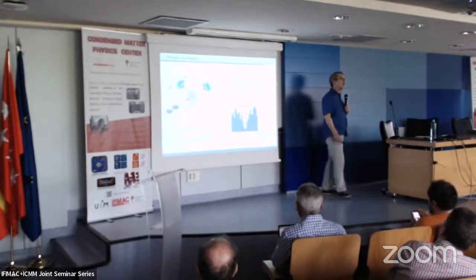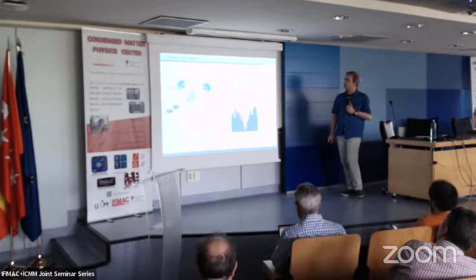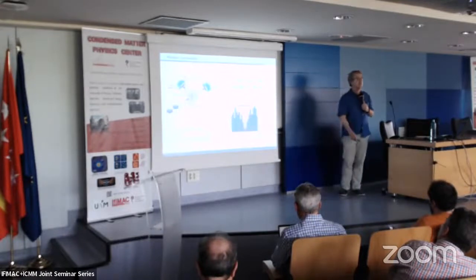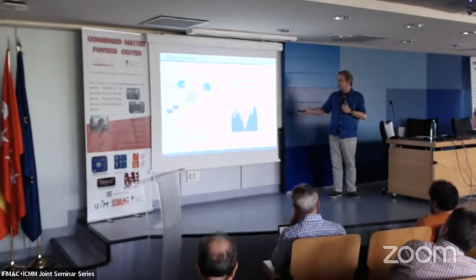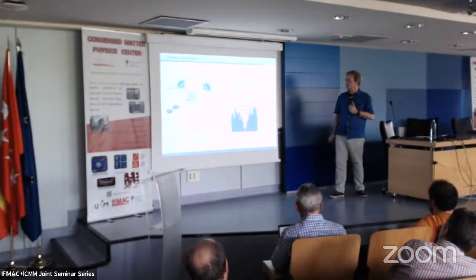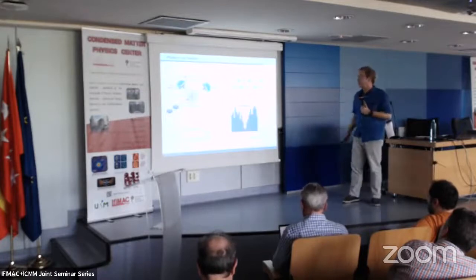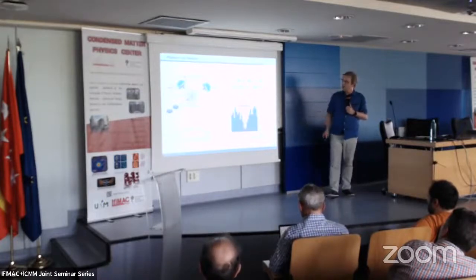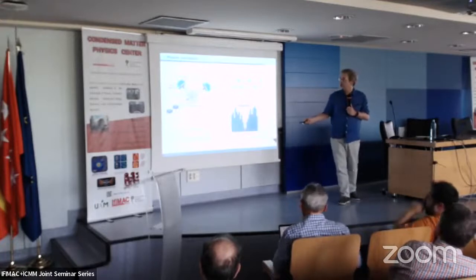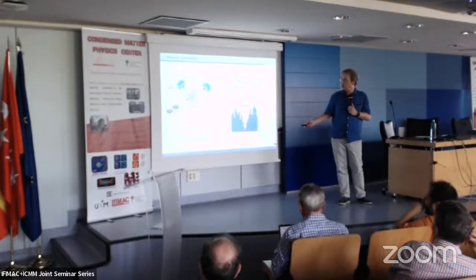Now, if you make a histogram of all these different values of the delays between the photons arriving in the 2 detectors, you can see that here at 0 delay there is a dip, meaning that at 0 time delay there are no 2 photons. So there are no 2 photons emitted at the same time. That means we really have a single photon emitted. This histogram is a representation of the correlation function, which is depicted here, and which measures the correlation between the 2 intensities, normalized by the intensity of the one and the intensity of the other.